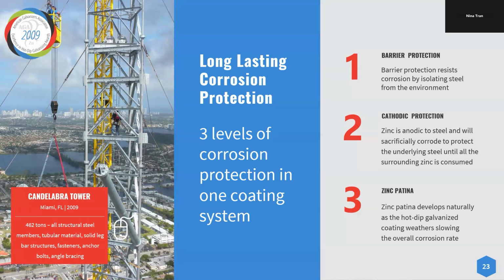Cathodic protection. Now we know on the galvanic series of metal that zinc is anodic to steel and will sacrifice itself to corrode to protect the underlying steel until all the surrounding zinc is consumed. So then you have cathodic protection. Then on top of that, you have the zinc patina. Now the zinc patina is unique to galvanized steel because it develops naturally over weathering cycles, wet and dry cycles. And this becomes zinc hydroxide and zinc carbonate build up on the surface and actually develop the zinc patina,